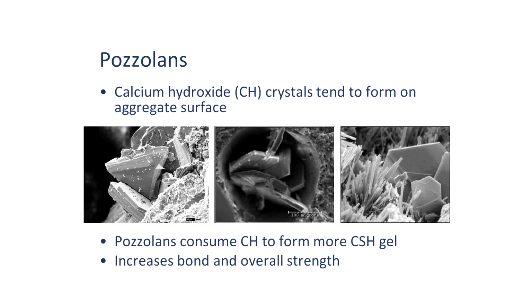These are scanning electron microscope photographs of calcium hydroxide crystals, and those are the big, really sharp, angular-looking, flat, platey things. If you can see my mouse, that's some right there. And this is the outside of a tiny sand grain. This is a pore, an open bubble in the cement paste, and there are some crystals that have formed. 100 microns, if you could take a human hair and cut it in half, that's the width of a human hair right there, 100 microns. And then over here we have the big flat platey crystals forming. And these long, slender things that look like fibers are actually ettringite crystals that formed in the concrete. But mostly what we're looking at here is the calcium hydroxide crystals.